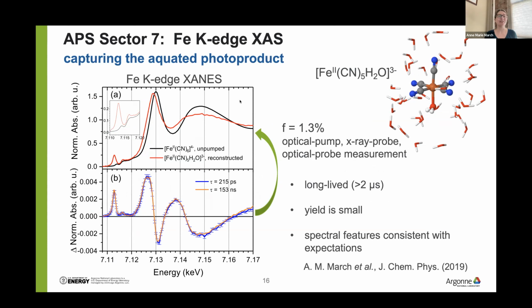Here's how we've gotten hooked, studying the sample with X-rays. We measured the absorption spectrum at the iron K edge, and the top here in black is the ground state spectrum. Here we were just pumping at longer wavelengths so that we were studying just the aquation reaction. We were wondering, can we catch the photoaquated product? The yield is extremely small, the optical absorption coefficient is very small, and we're going to make just a teeny tiny bit of this. Can we even capture the absorption spectrum?